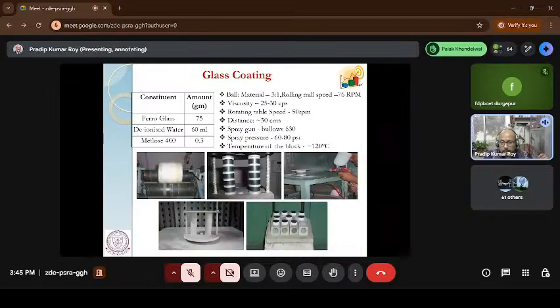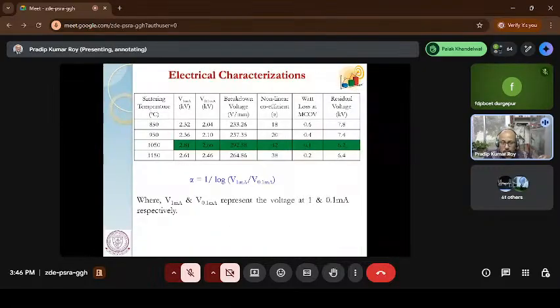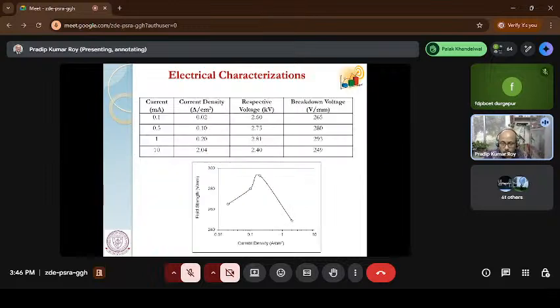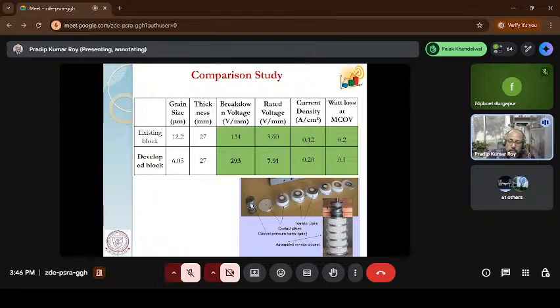So my energy handling capability is very important for the test to say whether the material is sufficient to keep the strength. After that, we assembled the surge arrestor, made the varistor, and made it a block surge arrestor around 11 kV. And we found that the rating of the block, earlier it was 3.6, now it is 7.91, more than double. So you can see here, just by reducing the grain size, I doubled the rating of the block.